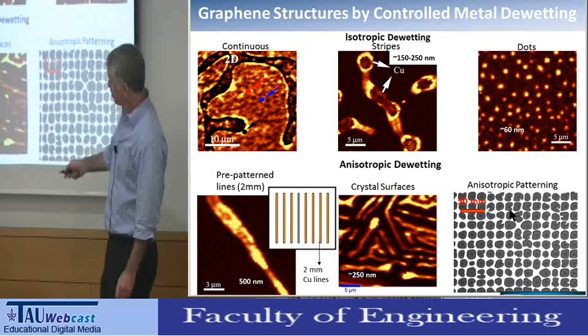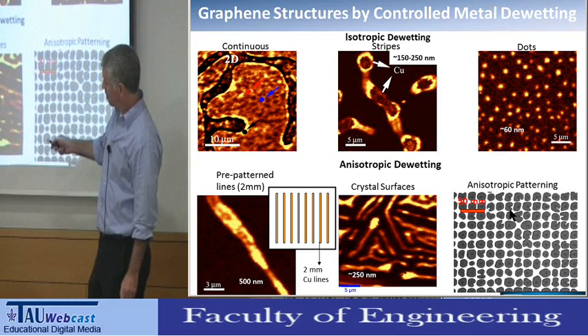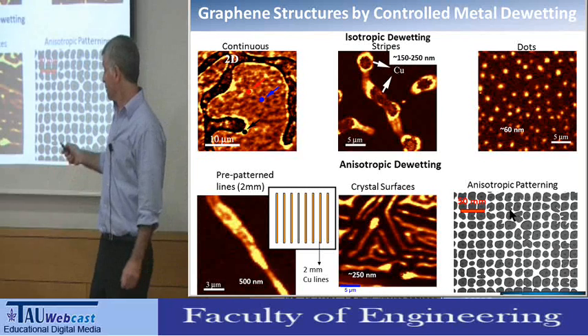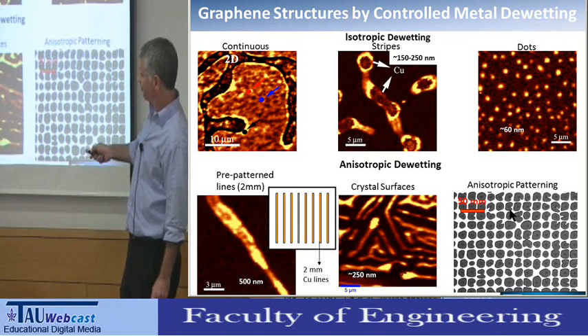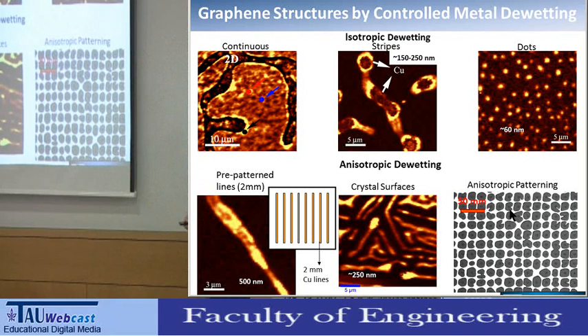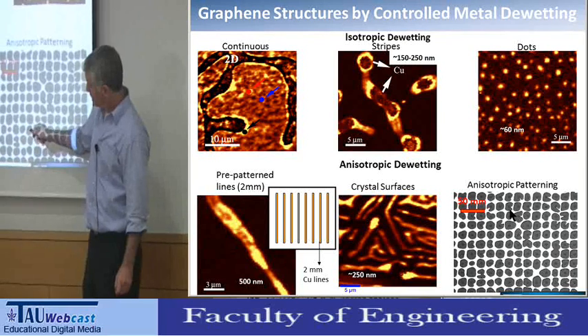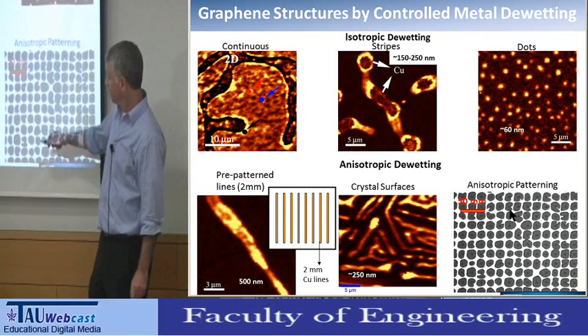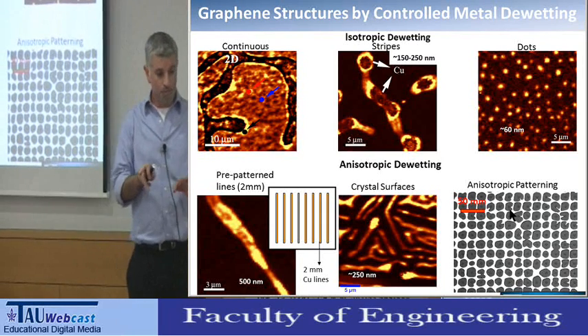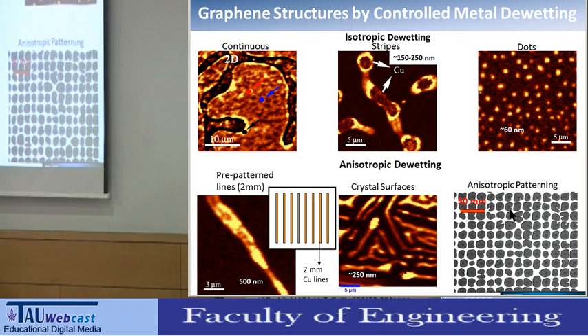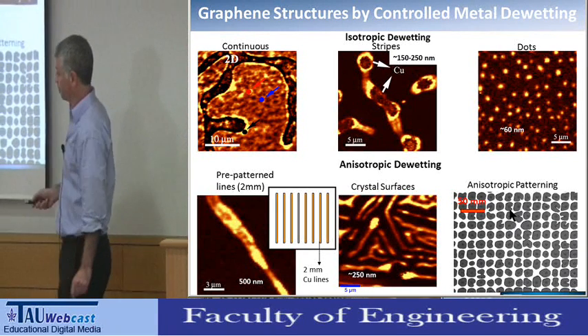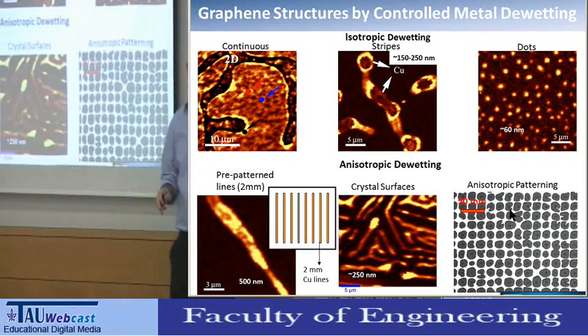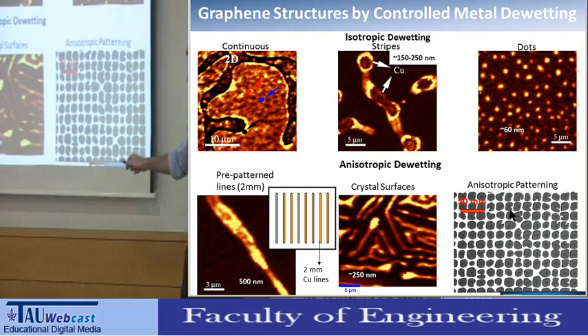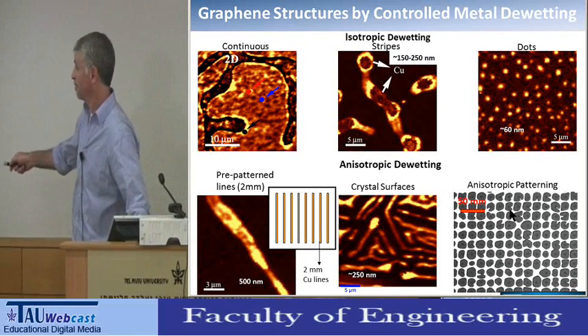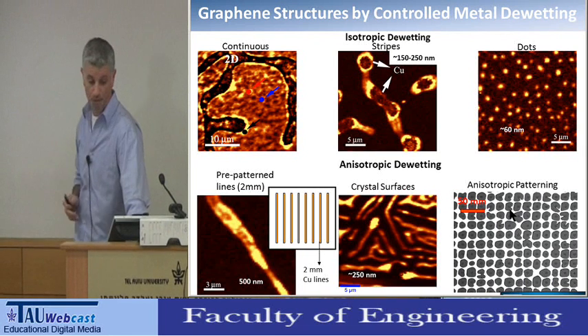As you can see here, for example, in this case copper lines were pre-patterned before the growth. And in this case, the anisotropic dewetting of the copper on C-plane sapphire was used to leave discrete stripes of graphene on the surface along the threefold symmetry lattice of the alumina, the sapphire crystal, as you can see here. So in between the lines here, there is no graphene. This is again mapping with the G peak here and here. Only when you get signal do you know that the graphene is there, and you can get stripes of graphene aligned along the lattice of the sapphire.